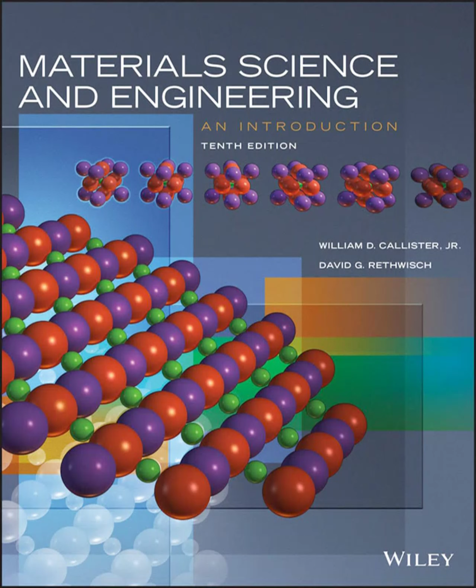Okay, so that's one way. What's the other? The second mechanism is interstitial diffusion. Now, this is for very small impurity atoms. Think tiny things like hydrogen, carbon, nitrogen, maybe oxygen. These atoms are small enough to fit into the gaps, the little interstitial positions between the larger host atoms in the main lattice. So these small interstitial atoms just jump from one gap to a neighboring empty gap. The key here is size. Larger atoms, whether they're host atoms or other impurities substituting for host atoms, they just don't diffuse this way.